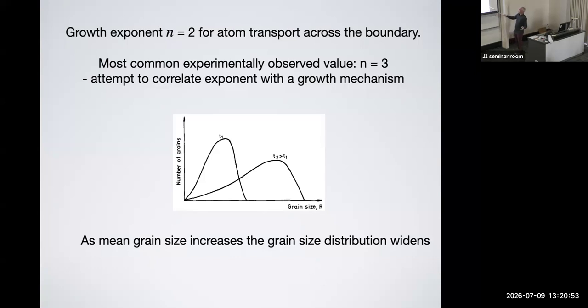The longer you run that, because from those grain growth models, you always have grains above a certain critical size that increase in size. Grains that are smaller decrease in size. So you develop this long tail towards small grain sizes. So your actual grain size distribution increases with mean grain size or with time, with growth time. So there are a few of these issues that, yes, complicate your modeling of grain growth behaviors.